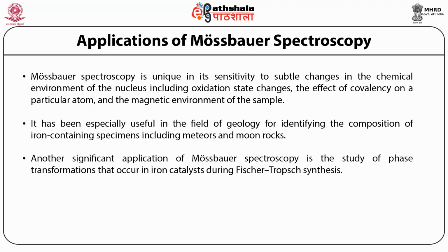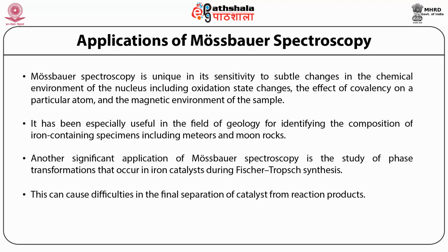Another significant application of Mossbauer spectroscopy is the study of phase transformation that occur in iron catalyst during Fischer-Tropsch synthesis. While these catalysts initially consist of hematite, during reaction they are transformed into a mixture of magnetite and several iron carbides. So basically, detection of these different kinds of iron based compounds is possible by using this spectroscopy. The formation of carbides appears to improve the catalytic activity. However, it can also lead to the mechanical breakup and attrition of catalyst particles. This can cause difficulties in the final separation of catalyst from the reaction product.